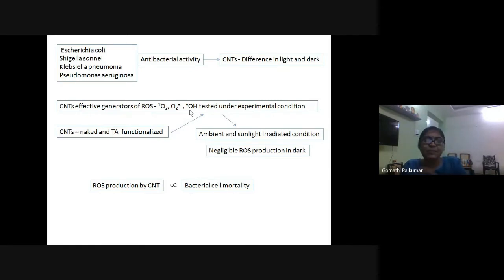So now the second thing we did was, we saw that the naked carbon nanotubes could produce oxy radical species; can the tannic acid functionalized carbon nanotubes also produce them? Then we found out that the tannic acid functionalized carbon nanotubes did not produce oxy radical species. Therefore, we confirmed that the true mechanism behind bacterial cytotoxicity, behind killing, was not puncturing. Carbon nanotubes did not puncture. Carbon nanotubes did not edge, which means they did not rub the surface. Rather, even though carbon nanotubes were not in contact with the bacteria, even though they were far from the bacteria, all the reactive oxygen species that are produced in the presence of light actually killed the pathogenic bacteria.